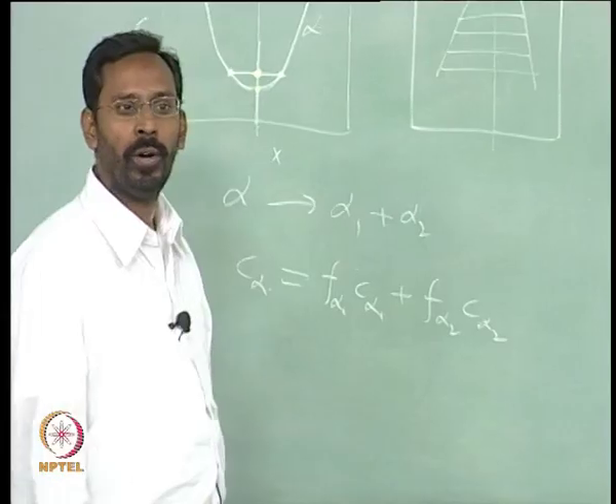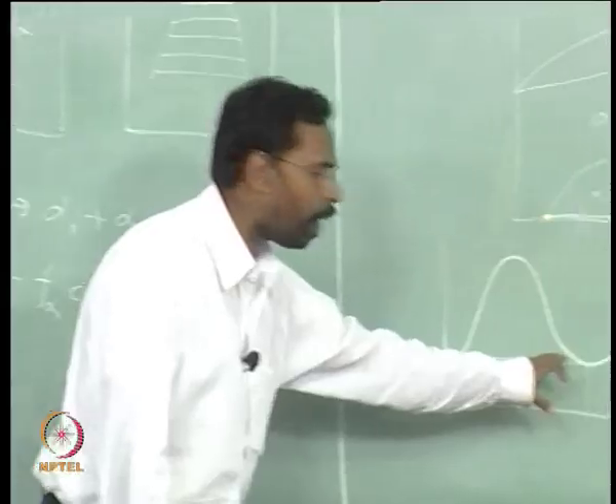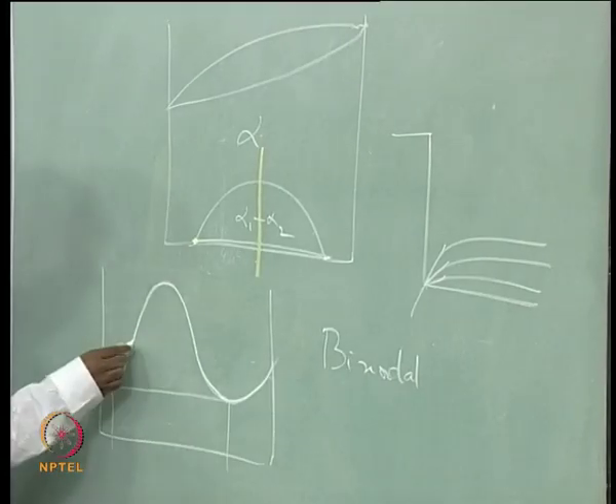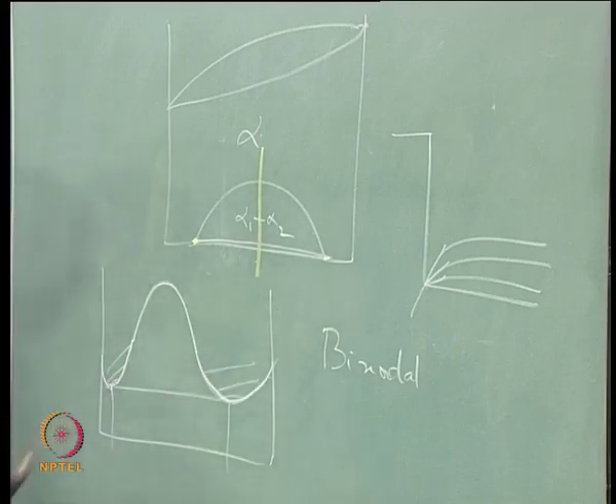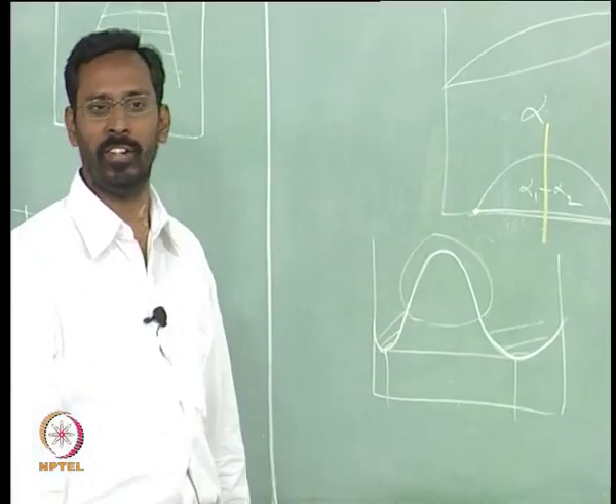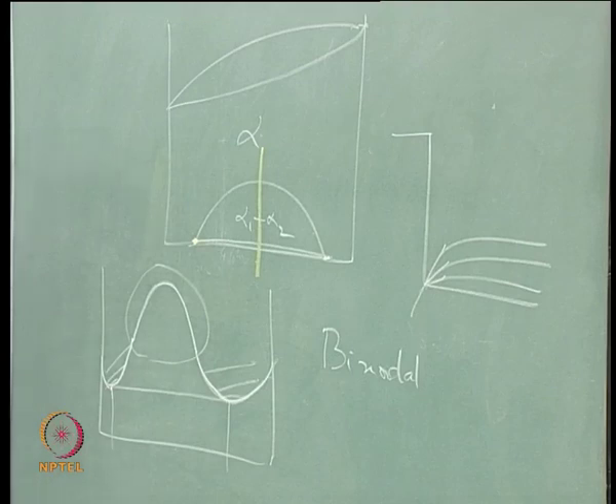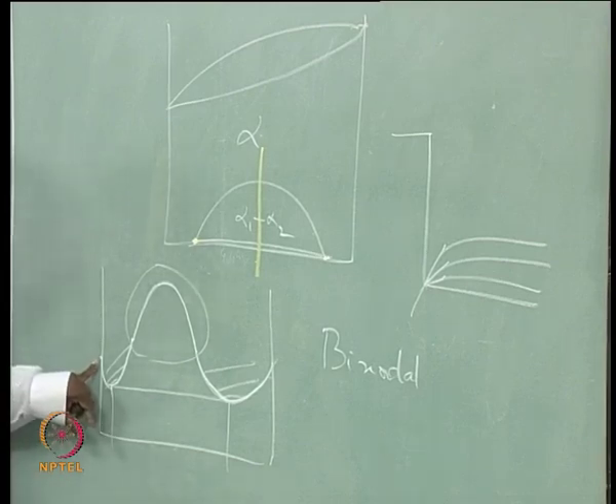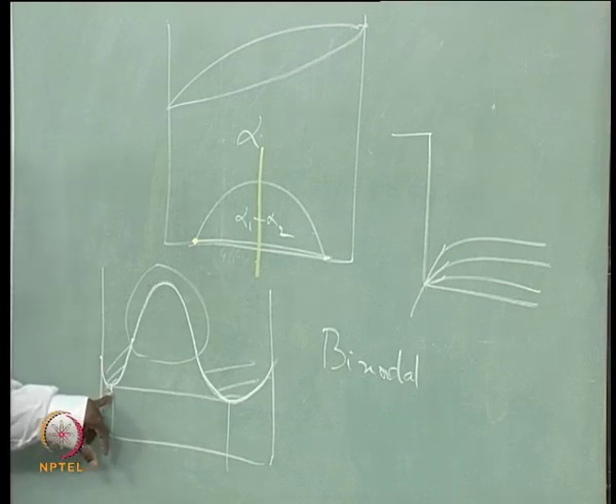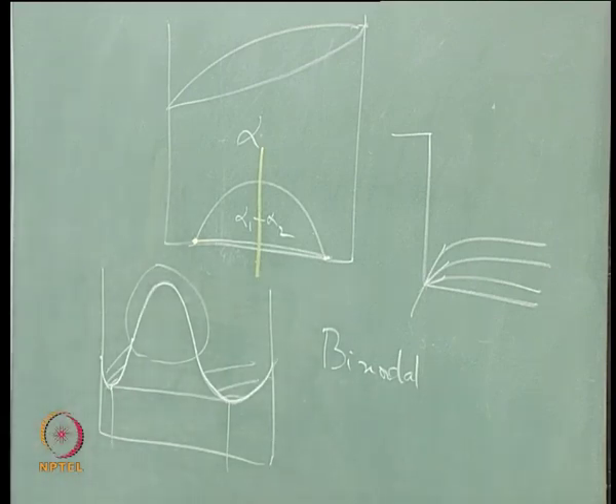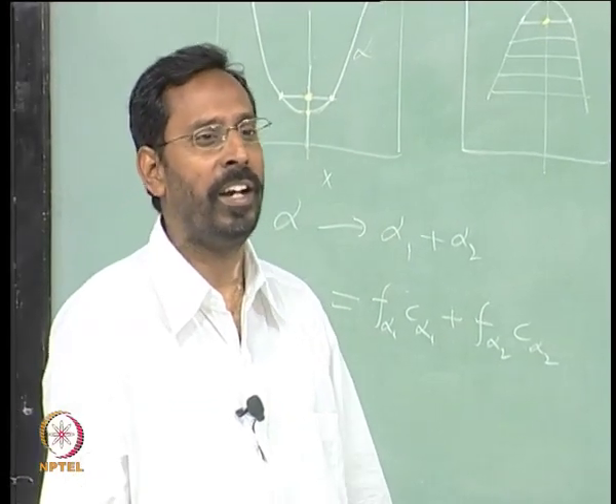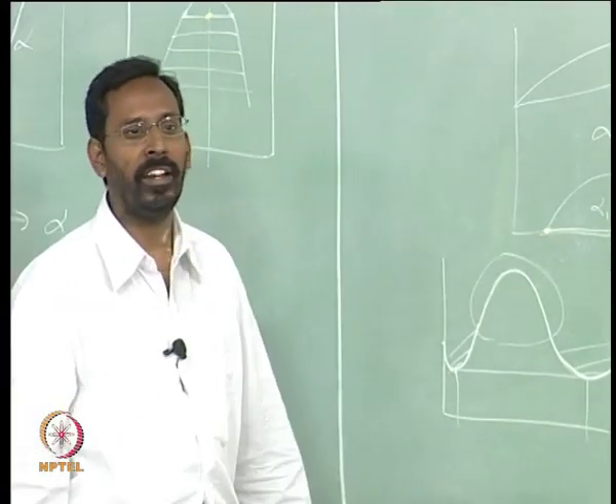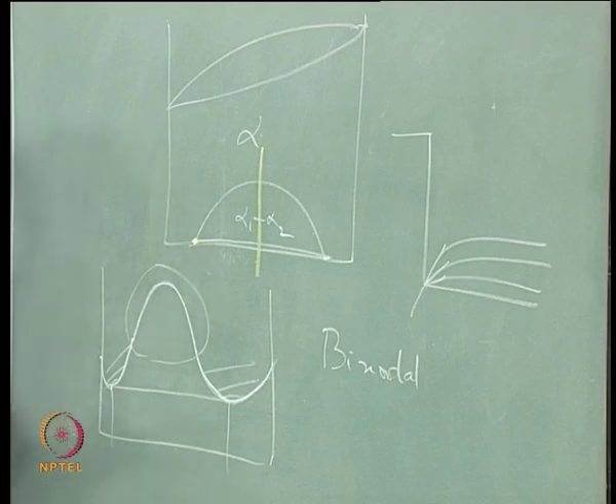If you look at these 2 curves, concave upwards and concave downwards. So, you have 2 parts here which are similar in nature, which are related to stable phase condition, and there is one region here in the middle, and that is the region where there is a change of slope. If you look at the slope of this free energy curve as a function of composition, what is it at the pure metal end? It is minus infinity. So, this minus infinity slowly starts increasing, and when you reach this value, it is not 0, it need not be, it will be 0 only when the tangent is horizontal, and the tangent need not be horizontal. So, it reaches a higher value.